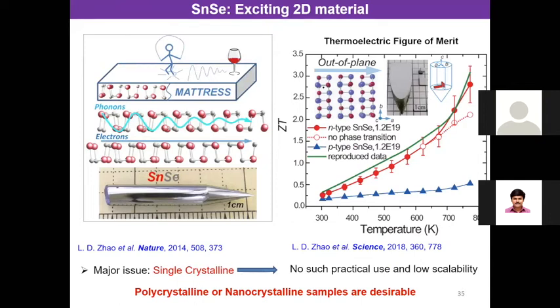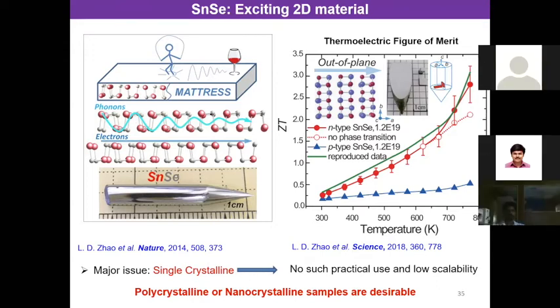Basically, this tin selenide, which is a sensation in thermoelectrics in the last couple of years, because three important papers, one Nature and two Science papers, came in the last 4 years about this tin selenide, where it shows it has a layered structure, and due to this layered structure, it has a significant amount of anharmonicity. All of you know, I think, anharmonic potential like Morse potential and all. So it has anharmonic bonding, anharmonic lattice, which gives rise to ultra low thermal conductivity. And in single crystal form, please remember, in single crystal form, it gives ZT close to 3.